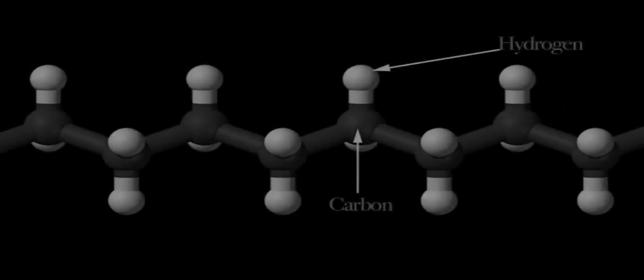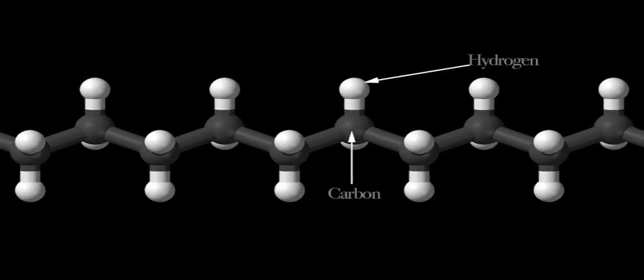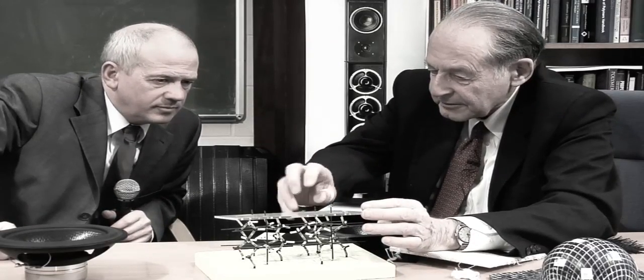Can you explain to me a little bit more about the process? When I use the term isotactic polypropylene, in my ignorance, I'm saying things which I have no idea what I'm saying. What is it I am actually saying when I say isotactic polypropylene? The thing is, if you take this sort of linear chain here, this is a model of polyethylene basically. So you have a chain here which has got nothing on it except carbon atoms. And that's why when you stretch it out, it becomes very strong. It's as if all the carbon atoms are arranged as if they were in diamond. But in polypropylene, you actually have what we call a side group. You have a methyl group. You have something on the side, and that makes it into a helix.